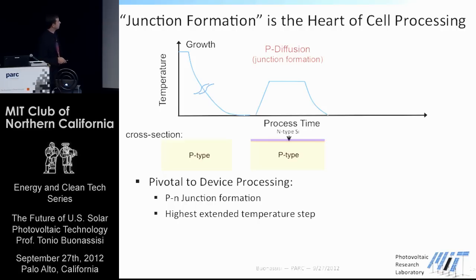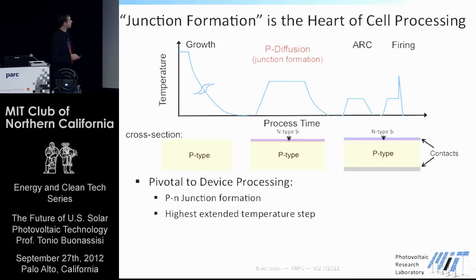Next, we have the formation of an anti-reflection coating that allows it to absorb light. And that's why silicon, which is normally gray, appears black right here. And we have the contact metallization that allows you to extract charge and utilizes 10% of the world's silver in the process, which is right here, the firing step to create these contacts. So if we look at the time temperature profile in schematic form, this right here is really the one process with the largest thermal budget, the largest amount of heat, right, that we can use to manipulate the defects inside